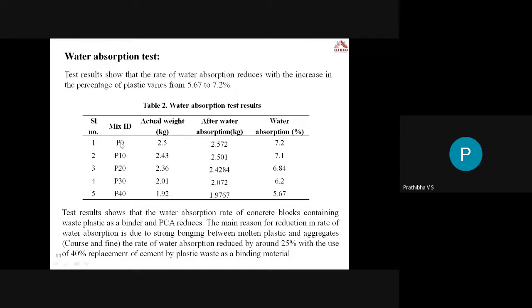Here the blocks are cast, the initial weight is taken, and they are soaked in water for 24 hours. After 24 hours, again the saturated weight of the blocks is taken. Then the difference gives us the water absorption. Here again, with the increase in the percentage of plastic, we can see that there is a reduction in water absorption. It is reduced by around 25%.